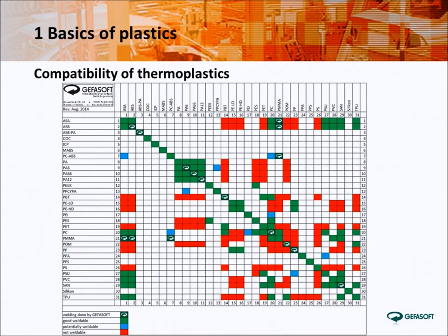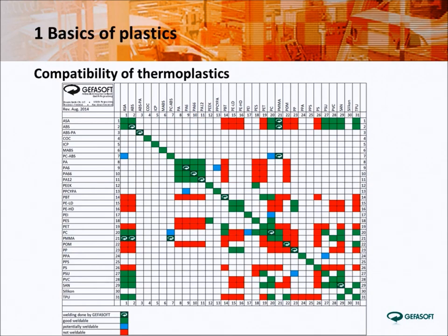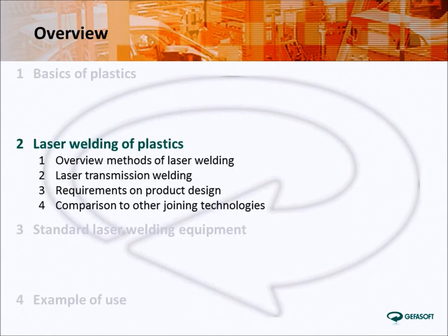The chart shows a summary of the compatibility of materials for laser welding of plastics, as well as some applications realized by GEFASOFT. Unfortunately, you can find only incomplete and sometimes inconsistent information about the welding results of material combinations in literature. Because especially fillers and additives such as pigments, flame retardants, mold release agents, and softeners have a significant influence on the welding result, a pre-study with material samples from the chosen supplier is advisable in any case. Considering these preconditions, we will proceed with the actual welding process.